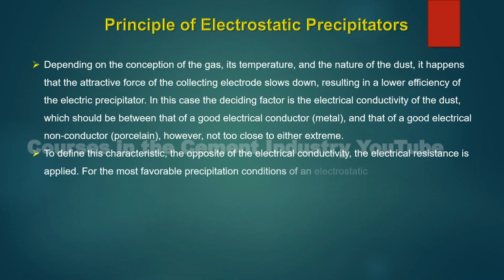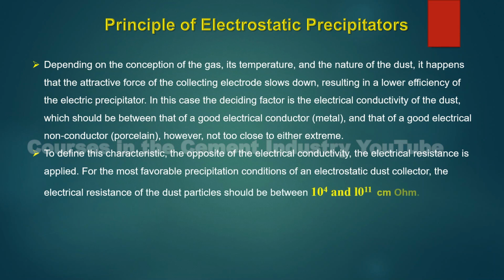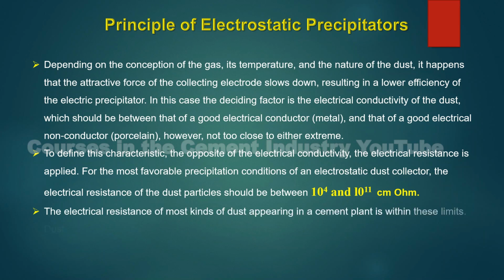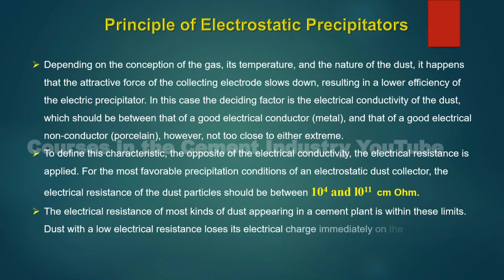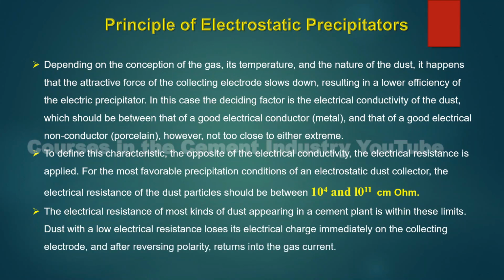For the most favorable precipitation conditions of an electrostatic dust collector, the electrical resistance of the dust particles should be between 10^4 and 10^11 ohm-centimeters. The electrical resistance of most kinds of dust appearing in a cement plant is within these limits. Dust with a low electrical resistance loses its electrical charge immediately on the collecting electrode, and after reversing polarity, returns into the gas current.